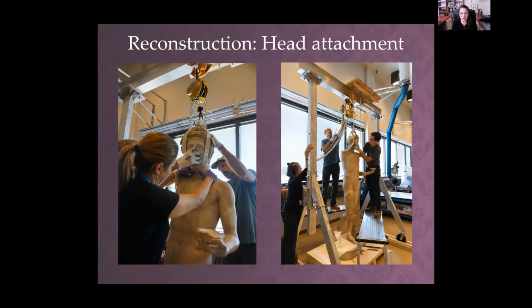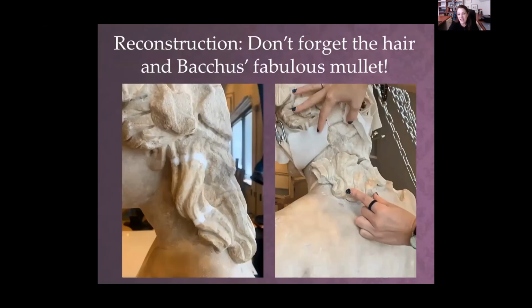So we had it all planned, we had it structurally stable, and the head had to stay supported in this gantry for 3 months while the solvents for the adhesives evaporated, and we knew that it would be structurally sound to take it out of the gantry itself. And once we did that, we also realized that the mullet had to go on afterwards.